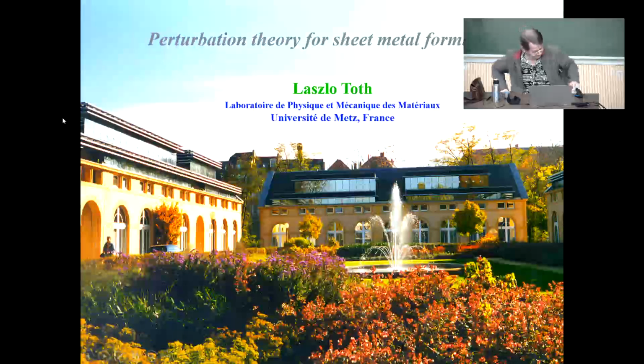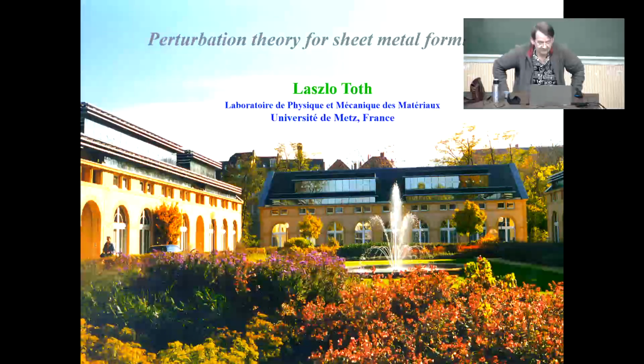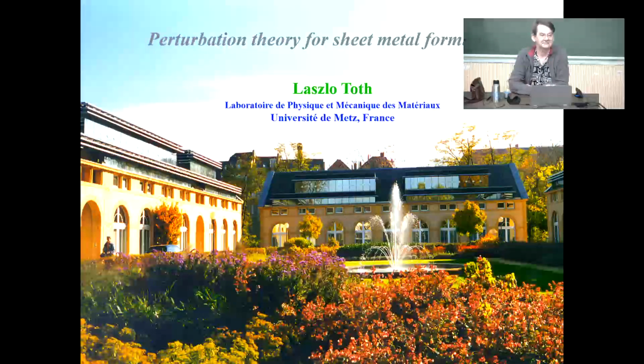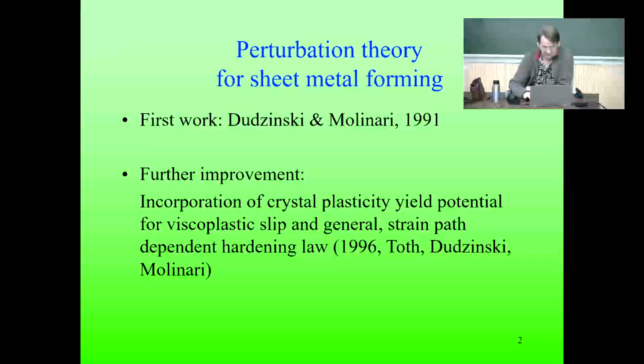This is more general, I believe, and different from this initial defect theory, because here the defect will be assumed not only for the thickness variation, but for all the parameters which are in the process. Much more general. So the first work, establishing the theory itself, was done by Dudzinski and Molinari in 1991. And then when I arrived to the lab there, we developed in 1996 how it works with polycrystal plasticity and strain path dependent hardening, so in the most general case.